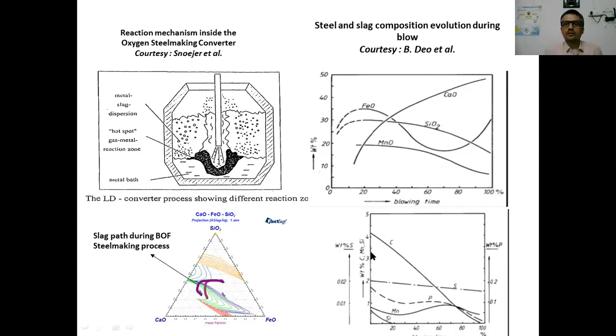If you are talking about the removal of impurities present in the liquid melt, you can see that silicon is getting oxidized in the first 3 to 5 minutes, the first 20% of the blow, because silicon has a higher affinity towards oxygen, whereas the removal of carbon occurs continuously. The phosphorus removal occurs either in the middle part of the blow or in the last part of the blow, because it requires a highly basic slag and a slag which is rich in FeO.